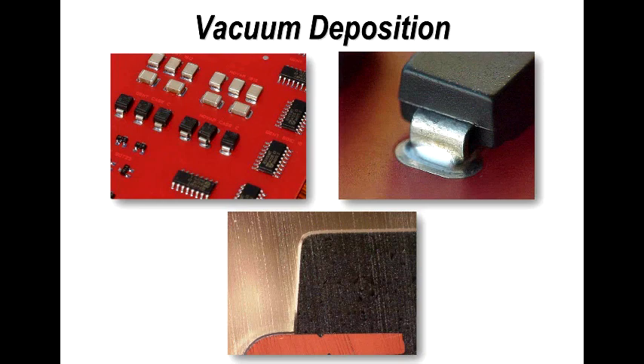Now, one of the disadvantages of the parylene coating, although it's supremely accurate in terms of the thickness applied to a printed circuit board, is that it is difficult to see. Many of my friends say, no problem, you can inspect it, you can see it. I don't believe that's true, and I've inspected many boards. As the coating thickness builds, as it's much thicker, possibly you can see it. Now, there are materials which have a UV trace in, and up until, I guess, the last few years, parylene did not have a UV trace, and I'll address that in a moment.